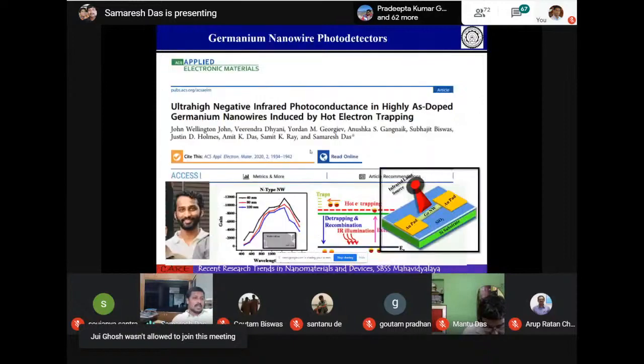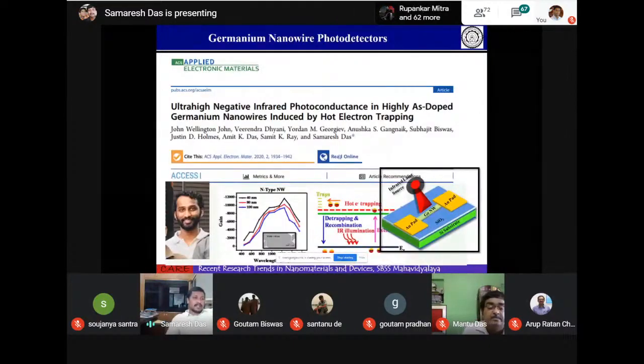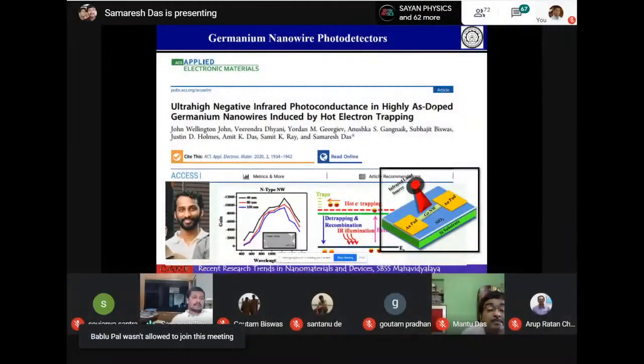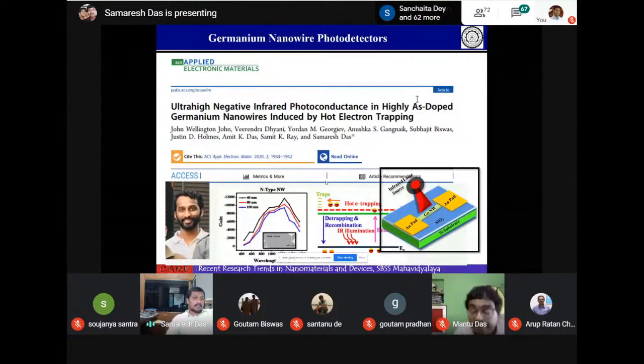And also we are working on the infrared region. For the infrared region, silicon is not that good, so we are going for germanium nanowire detectors. And in all this technology, the previous ones and this one, we have gone for top-down technology. We take a wafer and then pattern it by e-beam lithography, so you can make an array of detectors, anything. It is not like you take a single nanowire and then make the contact. For this germanium nanowire, we have reported a very high gain in the infrared range, more than 1 micrometer, and the gain is 10 to the power 4. It is a very high gain because of the nanowire.